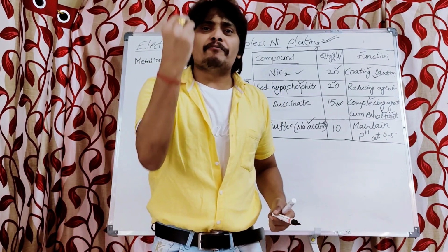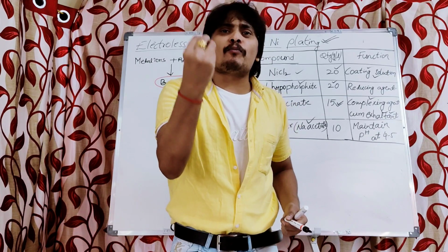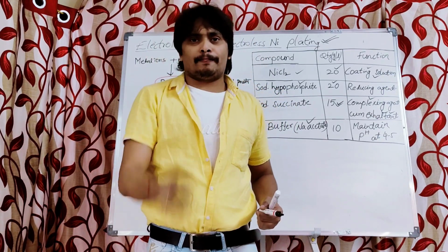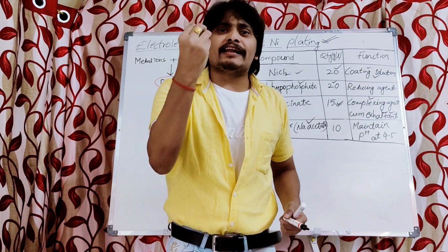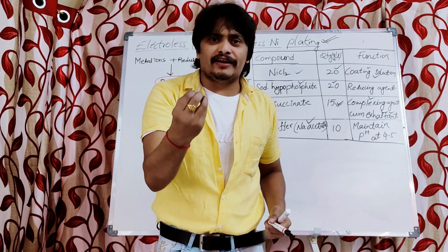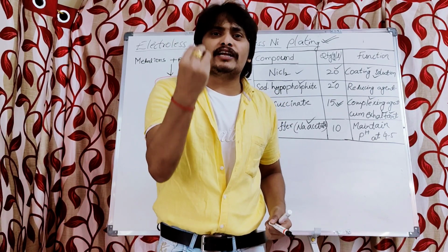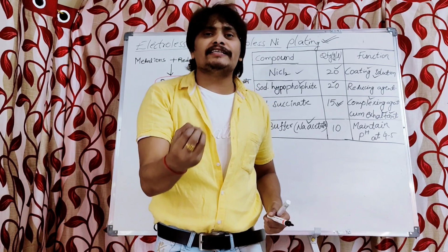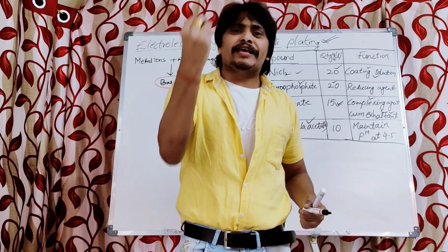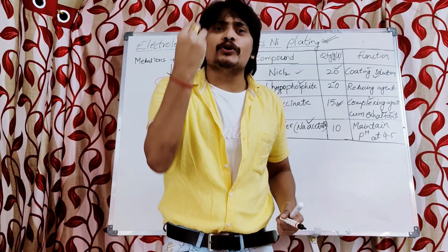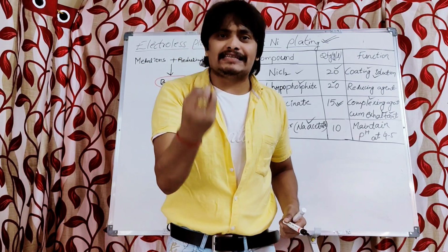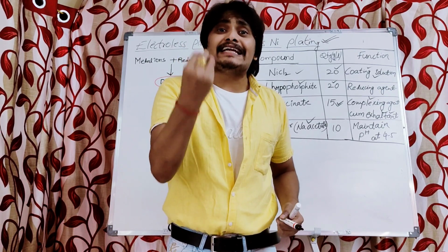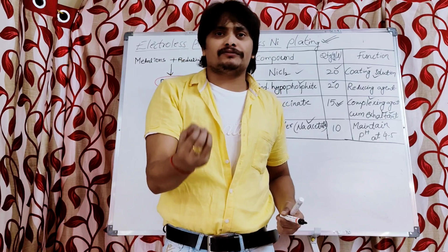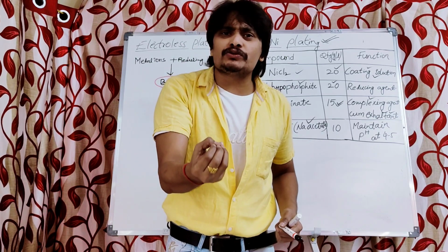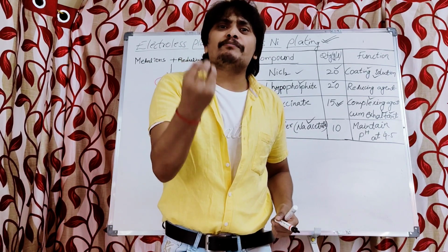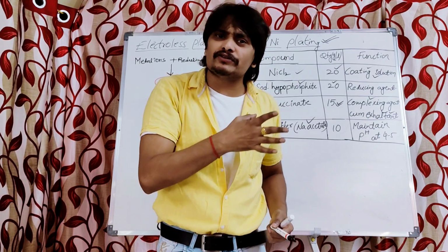So whenever we maintain the pH of 4.5, then only the reaction occurs between the coating solution, nickel chloride, and the reducing agent. And in order to maintain the pH 4.5, we have to use sodium acetate as a buffer solution. Now, what is a buffer solution, students? The solution which maintains the pH of the solution is nothing but the buffer solution.